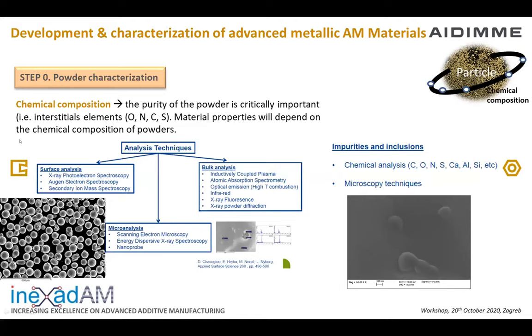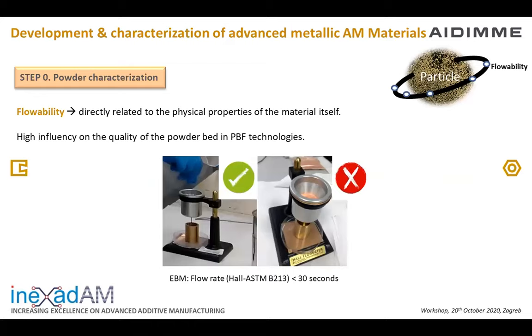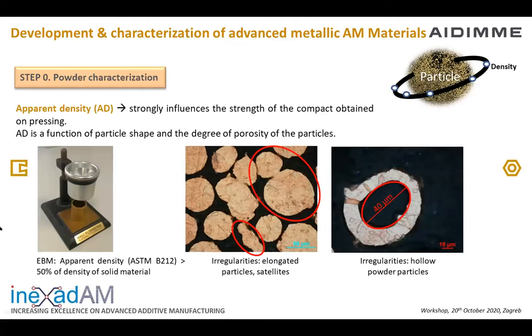Chemical composition is also important. The purity of the powder is critically important. For example, oxygen, nitrogen, carbon. As I said before, the oxygen increase led to a different microstructure. So the material properties will depend on the chemical composition of the powder, and it's important to check this property. Flowability is directly related to the physical properties of the material, and it has an influence on the quality of the powder bed in these technologies. Apparent density is a function of particle shape and the degree of porosity in the particles. Here is an example. You can see some irregularities.